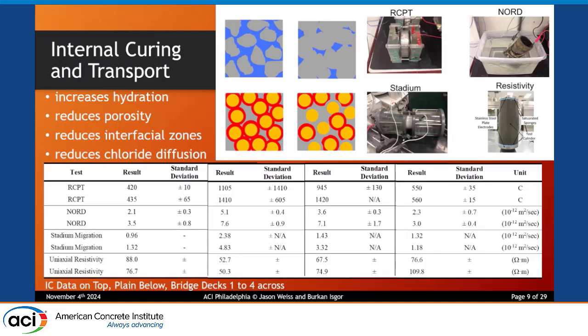Those calcined materials will react with calcium hydroxide and form hydration products. That happens at the surface of the aggregate, so you no longer have this interfacial transition zone. The surface of the aggregate is actually reacting with the calcium hydroxide, densifying it, so you lose those interfacial transition zones. Now you may have poured a 0.43 water to cement ratio concrete, but it behaves like a 0.36 because you've reduced those interfacial transition zones. You've cut down on that preferential path.